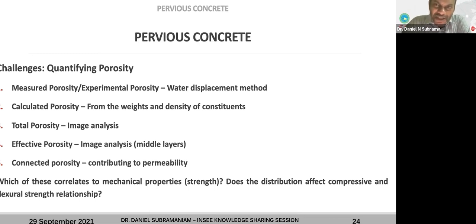And effective porosity is devoid of the boundary effect that we have on the top and the bottom, because when we are casting in the laboratory, we cast in molds, and the molds have a rigid surface, and the rigid surface is going to induce some kind of boundary effect. So we will talk about that later today. And the connected porosity is something that we still couldn't find out, because we are measuring the permeability separately, but we will not be able to talk about the connected porosity because it's a 3-dimensional effect.